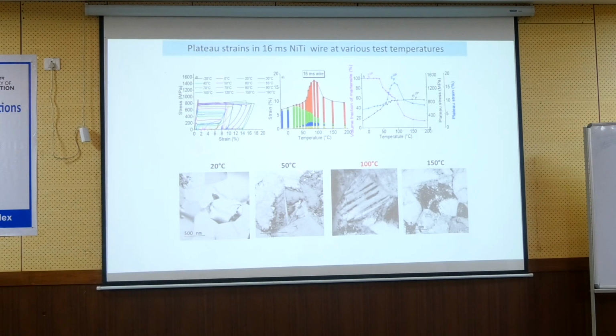It is all in austenite because we do unloading and then heating, and the material is in austenite at room temperature. And when you look at it at austenite. At 100 Celsius, where the plateau strain becomes large, so there is still plateau. The plateau strain, you see it's almost 16%, very, very long. You don't see it normally, but if you go to high temperature, you will see it.